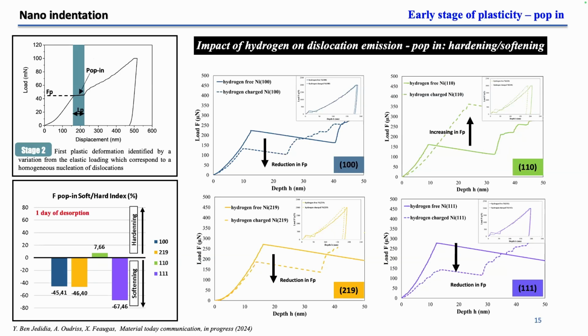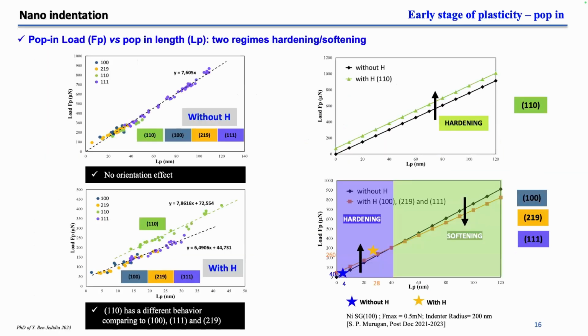And we show that we have here a reduction of pop-in and here an increase. And we have a competition between hardening and softening, independent of the orientation. And we show that the pop-in can be represented by a linear curve relating the load and the length, and is classical for the burst process. And we show that for the orientation 110, we have a hardening effect of hydrogen. And for the other orientations, we have a competition of hardening and softening, which depends on the length.